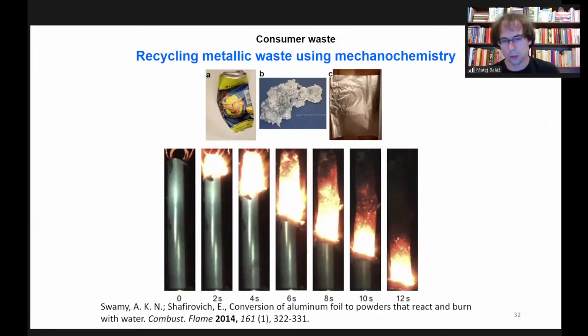Another subgroup of metallic waste is aluminium waste. So here we can see, for example, in C, we have aluminium foil. Everybody knows it, works with it often. And in the work which I am referencing here, the authors used aluminium that is present in this foil to initiate a reaction with water, actually. And they have a combustion reaction. You can see how the reaction front propagates very quickly. So they overcame a barrier which aluminium usually has in reaction with water. Due to the effect of mechanochemistry, such a reaction was possible.